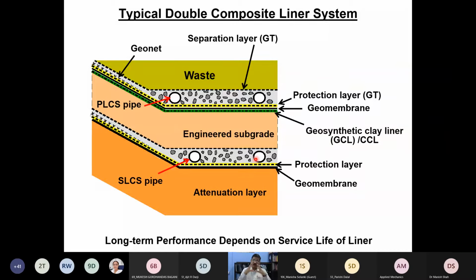If you look at the overall performance of this kind of double composite or single composite liner system, of course, all other system components also contribute to the overall performance. However, the long-term performance, the service life of the geomembrane and the GCL, is going to contribute significantly when compared to the others. As a result, in the present lecture we will talk about how the service life of a geomembrane is going to change under a given condition, how to assess the service life of a geomembrane, and if the service life is compromised, what would be the impact of the loss of service life on the surrounding environment.